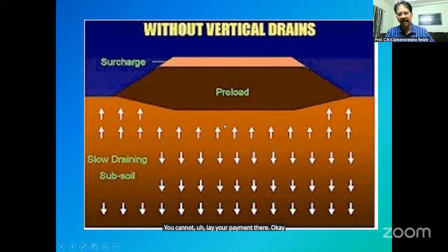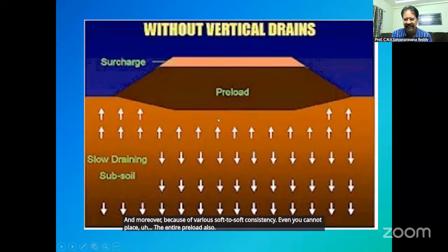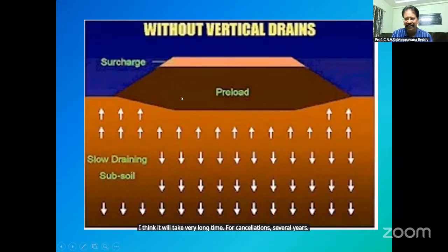Earlier also, for the runway, strengthening of soft clay was done using PVDs and by application of preload. Without improving drainage conditions over the existing soft clay, if I place a preload simulating the loading from my proposed structure, will it be of any use? No doubt pore water pressure will increase, but for dissipating excess pore water pressure, water has to travel either in upward or downward direction depending on availability of drainage space. So it is as good as constructing your structure only. And moreover, because of very soft to soft consistency, you cannot even place the entire preload. First, it will take a very long time for consolidation, several years. Second, you will not be able to place the entire preload. It will result in shear failure of soil.